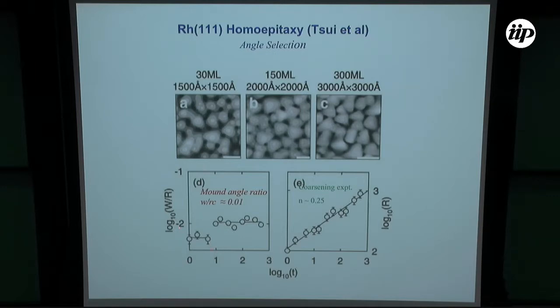This is a nice plot because it shows the ratio of the width to the length. So this is proportional to the angle. And what you observe is that, sure enough, after just a few layers, the angle stays constant. So these mounds are growing, but the step is selected. The plane is selected. The angle is selected already. And the coarsening exponent is roughly about a quarter in this experiment.